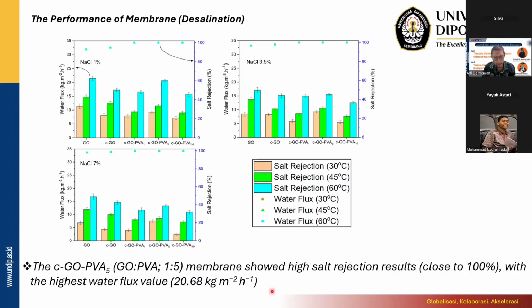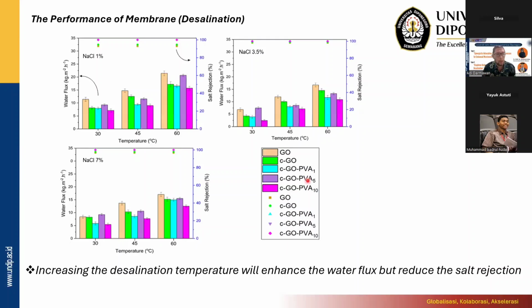Yeah. Okay, this is the performance of the membrane. Also, we test the temperature, yeah, room temperature, 30, 45, and 60. We can see that here by increasing the temperature, the water flux increases. It's easy to understand because by increasing the temperature, we increase the driving force of the feed water to pass the membrane. But we can see that even at room temperature, 30 degrees, the water flux is around 10. That means that we can produce pure water even at room temperature.